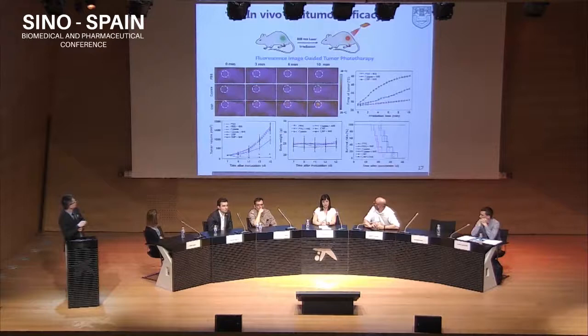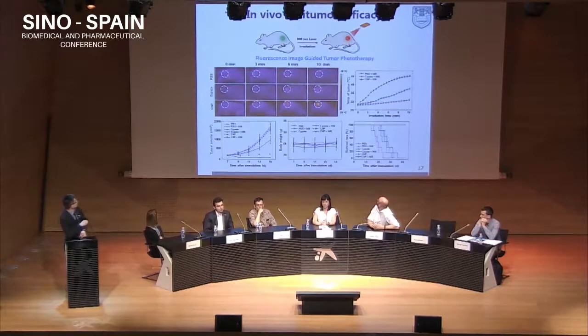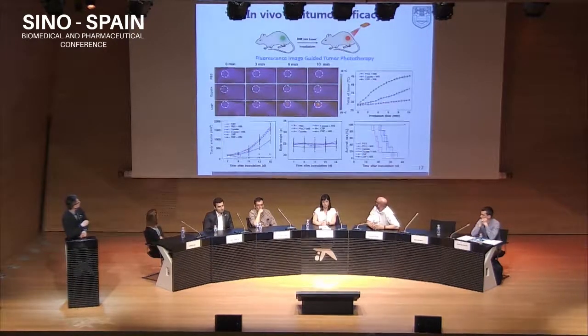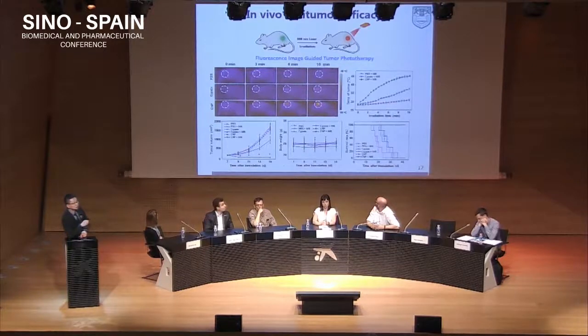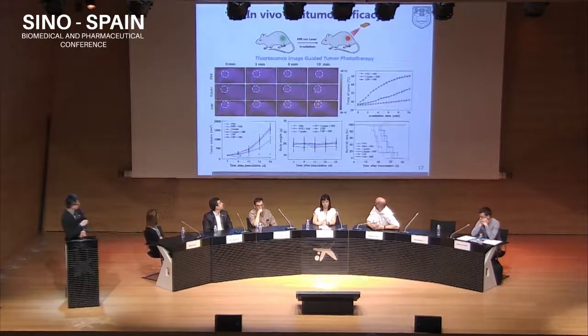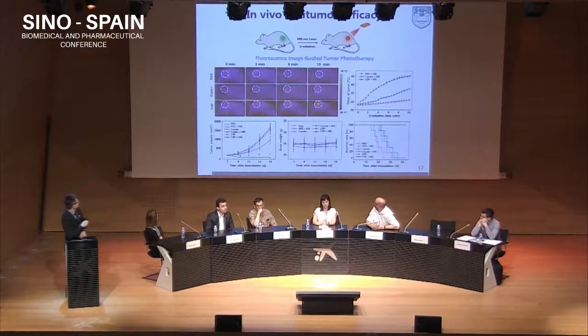Same, we irradiated the tumor by a laser. We call it fluorescence imaging guided tumor phototherapy, and also monitor the temperature change of the mice. We found the temperature increased by more than 14.5 degrees after 10 minutes irradiation. It also inhibited the tumor growth over 15 days, and also extended survival of the mice.